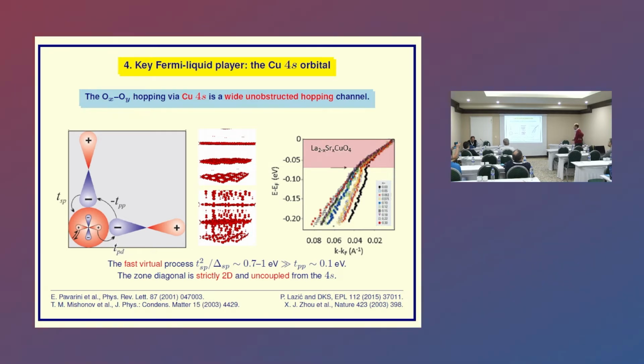And this is because the copper d orbital is blocked. It is blocked precisely by these strong correlations which we have been talking about. So the hole on the oxygen takes the easy way around. This overlap between the 4s orbital on the copper and the oxygen orbital is something like 2 electron volts. It is the biggest overlap in the game. And despite the fact that the s orbital is far away energetically, you have a second order process which goes like t squared over delta. And t is, as I said, 2, so t squared is 4. And if delta is 6, that's already 2/3.